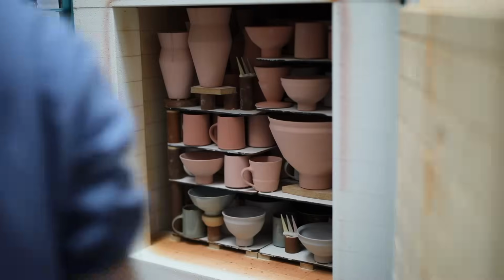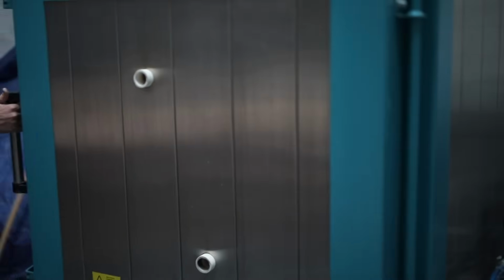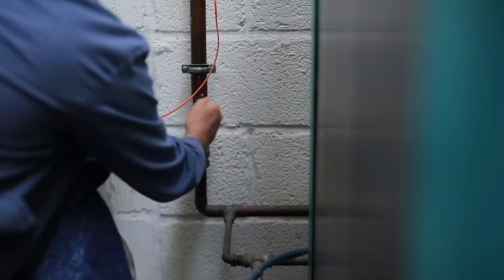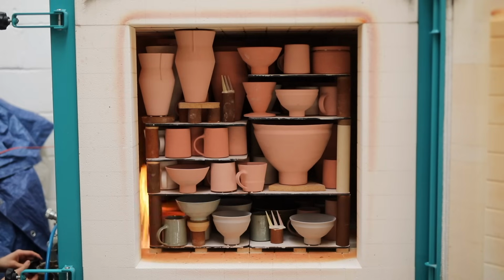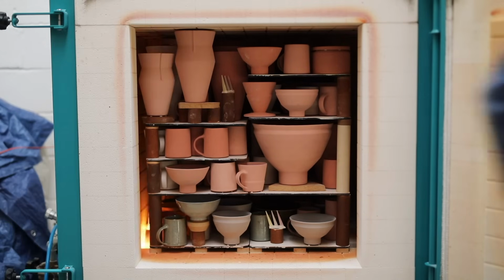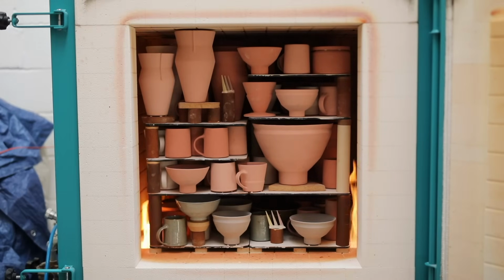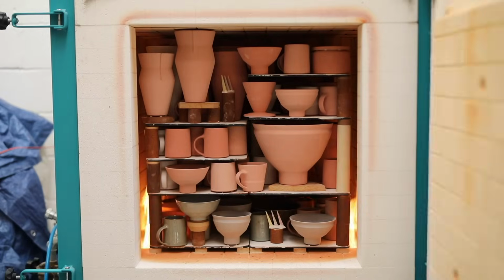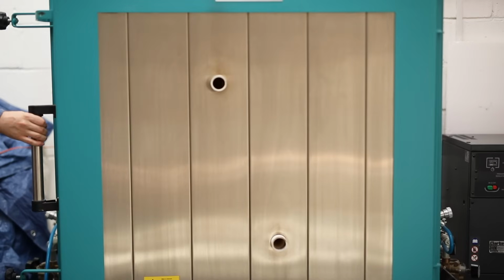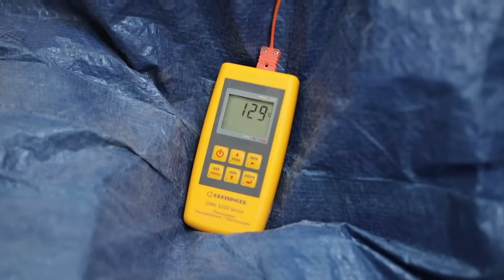With the kiln fully packed, I spend the rest of the day finishing off odd jobs and tidying up the workshop, and then tomorrow I'll come in really early and light the kiln at 7 AM on the dot. The gas is turned on, and then each of the 4 burners in each corner of the kiln are ignited. They're all set on the lowest possible setting, and I do all of this with the door open. This way gas doesn't accumulate inside the chamber, which is then suddenly lit, as this can lead to a small explosion. The door itself is then closed and sealed tight, and so begins the 9-hour-long reduction firing.